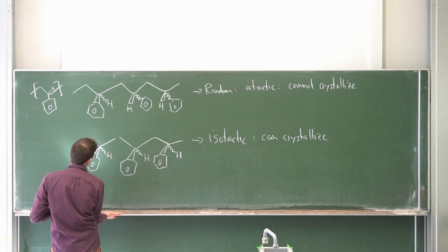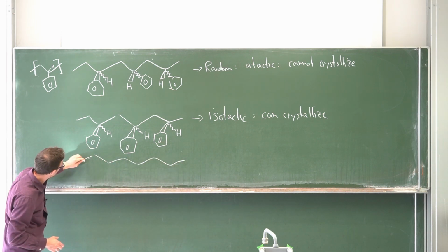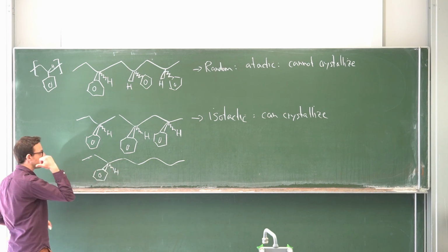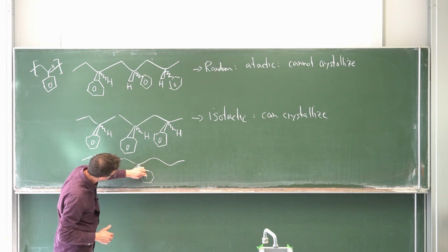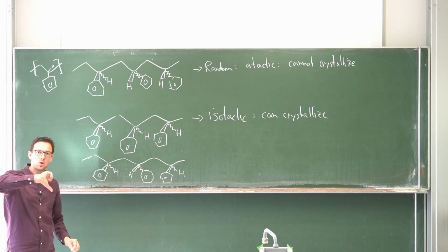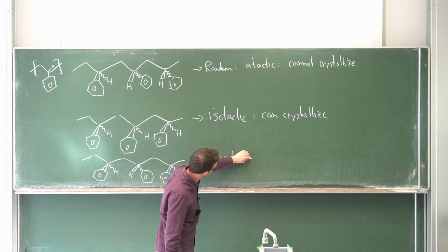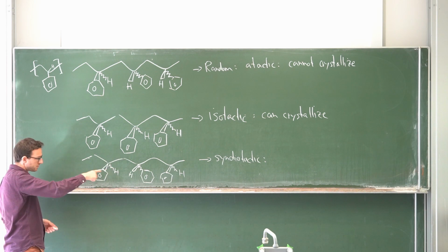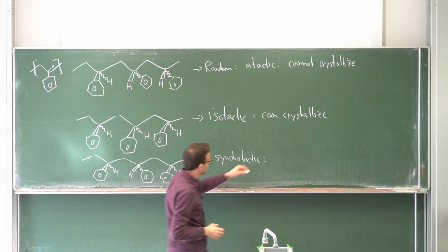And there was a third possibility, which I'm trying to squeeze in here, where it's always alternating. So the ring stands to the front, now the ring stands to the back, now it stands to the front again, and so on and so forth. So there it alternates all the time, which is called syndiotactic. And it's the same thing. Here you also have the possibility to stack the material in an ordered fashion, because all of them can align and the benzene rings can stick, or it doesn't need to be benzene, it can also be a different residue. They can form a crystal.